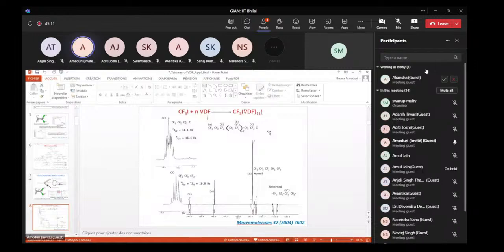What can you see? You can see the CF3 group in which the signal shows a quintet. And this is surprising because usually the CF3 is coupling with the CH2, the fluorine coupling with, and the fluorine is coupling with this fluorine in the beta position.